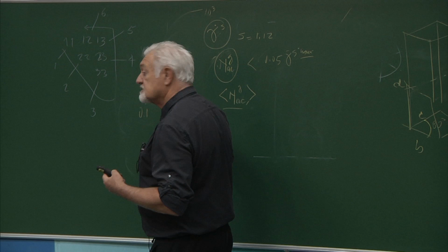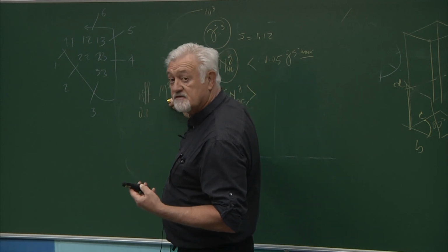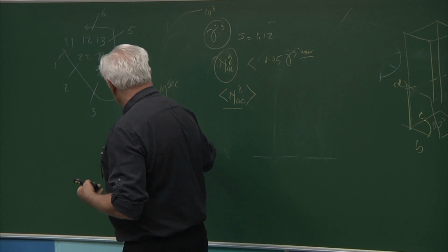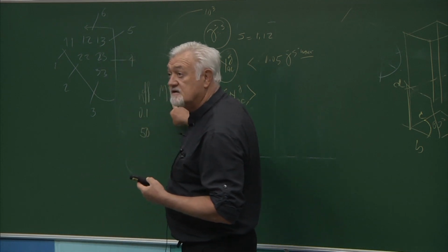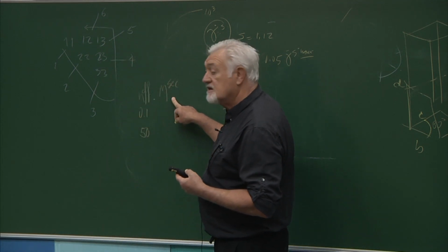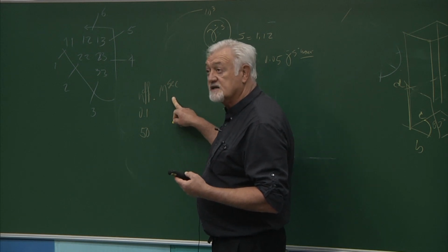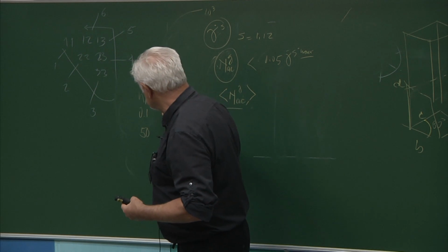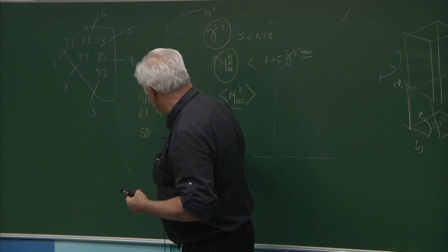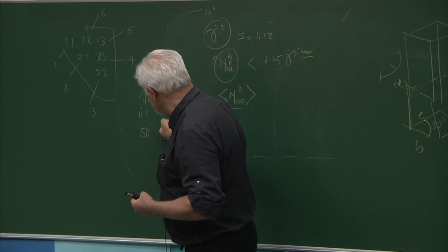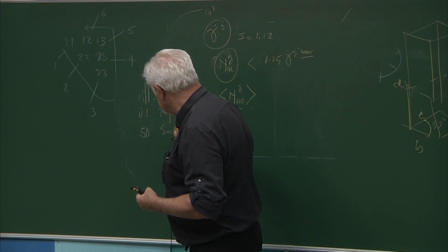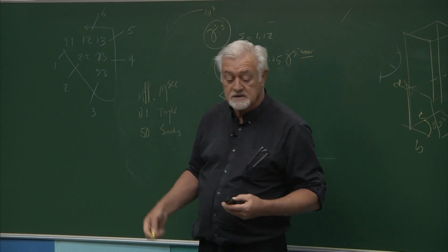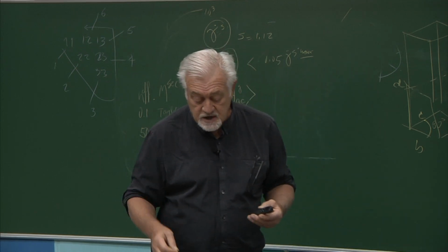So it's less and less compliant, more and more stiff. Now, if you multiply it by 50, you make the compliance of the medium very compliant, and then you are going towards the Sachs. So this one goes towards the Taylor model, and this one takes you to the Sachs model, and that is the n effective. But that is something that you can try yourself later.